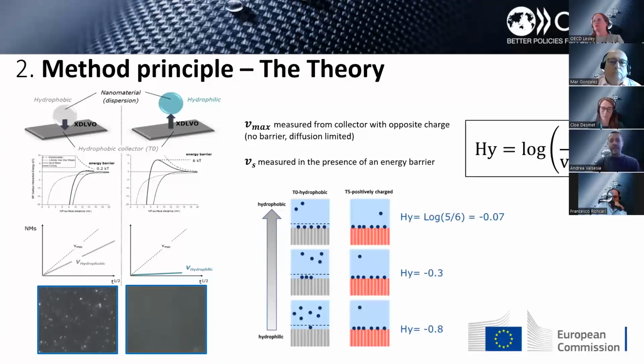The extended DLVO theory, which regulates the interaction between the particle and the surface, tells us that there is a very low energy barrier the particle has to overcome before getting in close contact with the surface and being immobilized. This energy barrier, calculated from the extended DLVO theory, is on the order of 0.1 to 0.2 kT, meaning thermal energy is able to make the particle diffuse and get in contact with the surface, becoming immobilized by the hydrophobic surface.